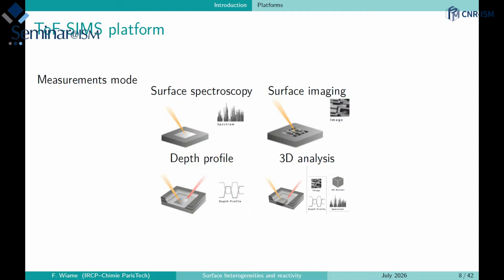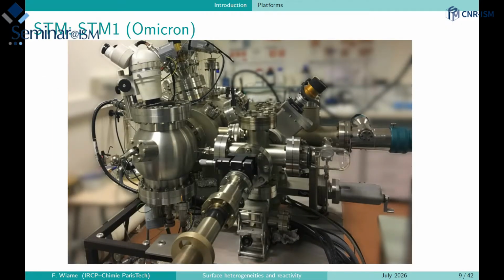And then we can combine the surface imaging and the depth profiling to have a 3D chemical mapping of the structure and identify some specific features. I forgot to mention that the lateral resolution that we have is limited to a few hundred nanometers, but it's generally enough to see some corrosion effects. So the last two equipment I will present you are the ones I'm in charge of. The first one is an STM-1 Omicron, one of the first systems sold by Omicron. In fact, I think it is the first one.